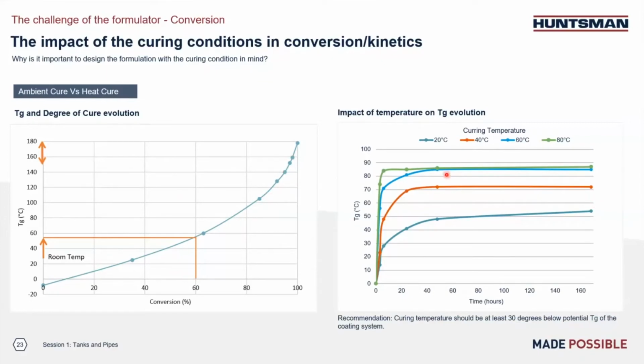This is a system with an ultimate TG of about 85 degrees C, right? And the same thing, if we cure at 20 degrees C, which is kind of a room temperature cure condition, you can see the TG is only about 55 degrees C, right? Still a big difference compared to ultimate TG. But if we cure at 60 degrees C, we can reach the ultimate TG, close to 85 degrees C. And if you want to cure at an even higher temperature, such as 80 degrees C, basically the ultimate TG is the same. The only difference is you just reach the ultimate TG in a shorter time, right? And so you always want to pick the right curing agent, so you can have a good degree of cure.